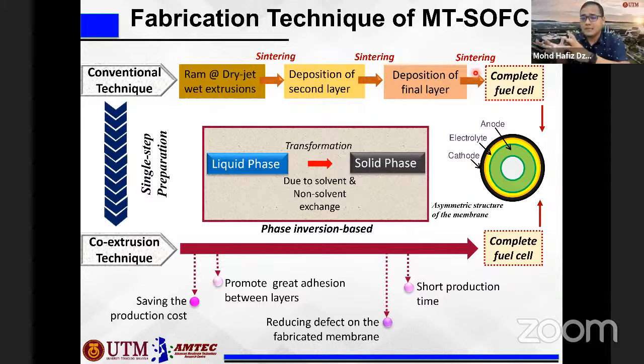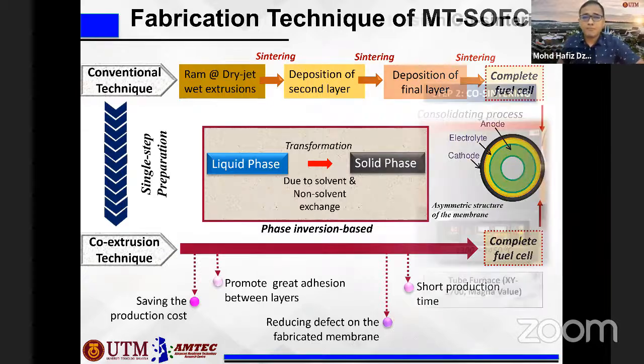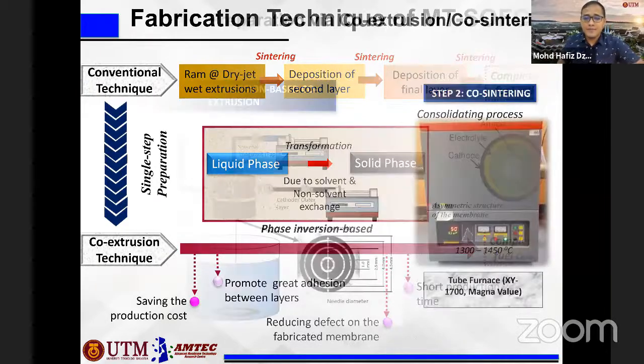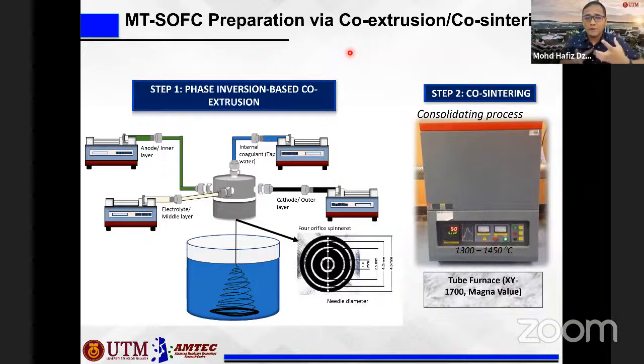in order to get a complete fuel cell. Okay, but we actually introduced a technique to produce a fuel cell in a single step, meaning that we can produce the 3 components simultaneously by using the co-extrusion technique. By having this technique, we can save a lot of production costs, promote great adhesion between the layers, and we can reduce the defects on the fabricated membrane and also shorten the production time. So this is similar to the step we use to produce the hollow fiber membrane.